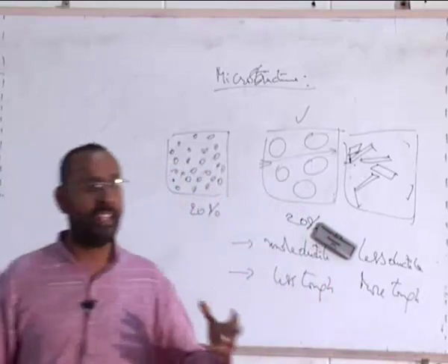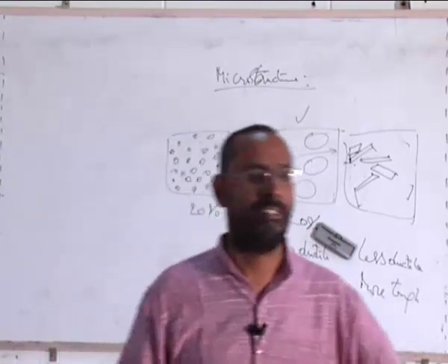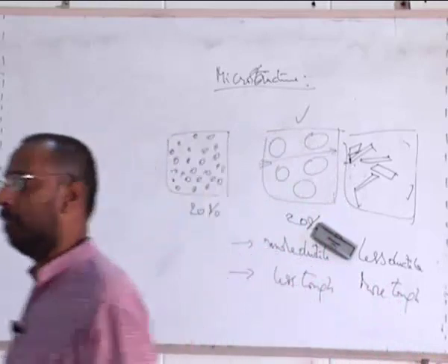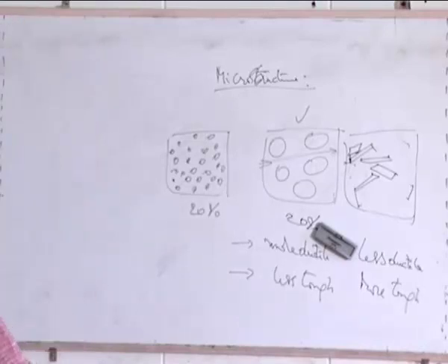That is why bainite is tougher than even pearlite. That's why people want bainite. The reason why people like bainite is that strength-wise bainite and pearlite may have similar strength, but toughness-wise bainite is much tougher than pearlite because of the acicular structure of the ferrite inside it.